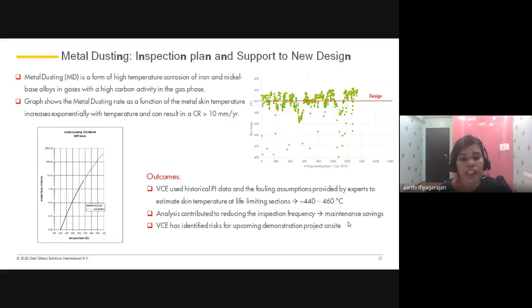In many of the oil and gas assets, such conditions exist in systems, for example, such as syngas, which is a combination of carbon monoxide and hydrogen, where you have both the reducing environment as well as high concentrations of CO, and it happens to a somewhat milder extent in steam methane reformers, where it is in the form of CH4, and it's not going to easily break into atomic carbon, and hence it happens at benign rates in hydrogen manufacturing units, also called HMUs in Shell. Now, fundamentally, the deposition of carbon on and within the affected metals and alloys is accompanied by disintegration of the substrate, and this disintegration will cause wall loss in industrial equipment and ultimately lead to failure of stressed components.